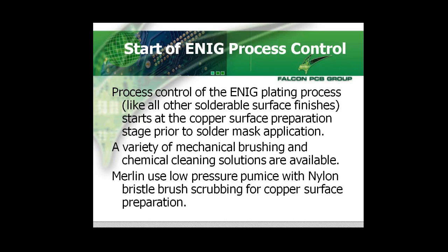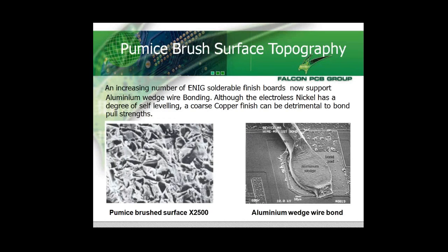With certain exotic materials like PTFE, where you cannot use any brushing or you'll destroy the adhesion properties for the solder mask, or very thin boards which could be damaged in a brushing operation, then we use chemical cleaning. The photograph on the left hand side shows a typical times 2500 pumice brush surface. This gives excellent adhesion for the solder mask and works extremely well, even for the aluminium wedge wire bonding finish.